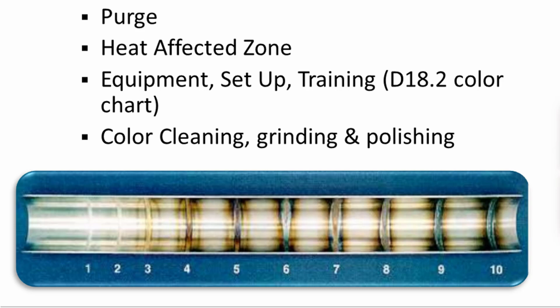1 and 2 can be very difficult to do, but 3 is what we typically expect and would want to see. As you get up into these other colorations, you start running into issues. We allow it if you remove the color, but particularly if you're running into products that have susceptibility to high corrosive environments, even with the color removed, you're going to set yourself up for potential corrosion because you've disrupted the structure of that metal significantly at the surface level because of the oxygen content that was allowed.